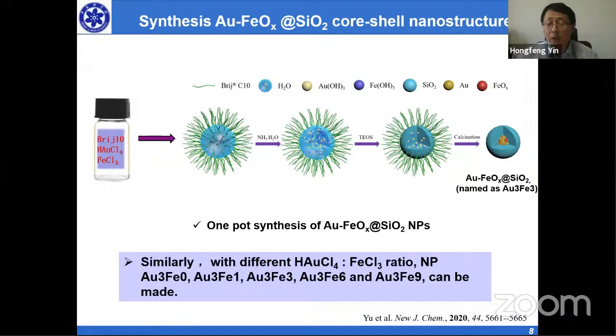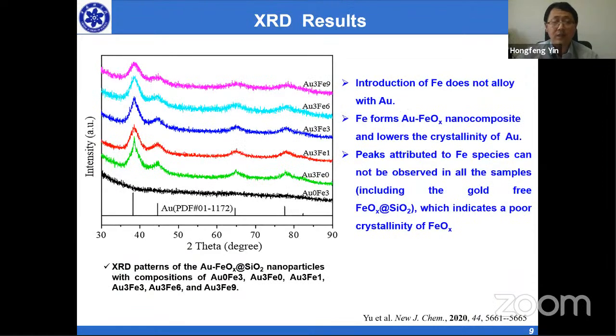I'll talk about the structure later. We can change the ratio between the gold precursor and the iron precursor, so we will have a different element ratio of the nanoparticle. This is the XRD of the particles we have made. We can say that with gold only, the peak is pretty sharp, and with the introduction of iron, it becomes not so sharp.